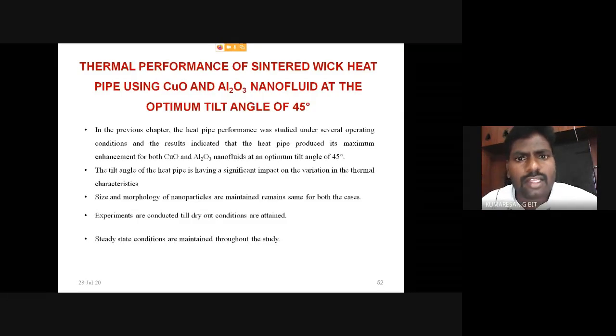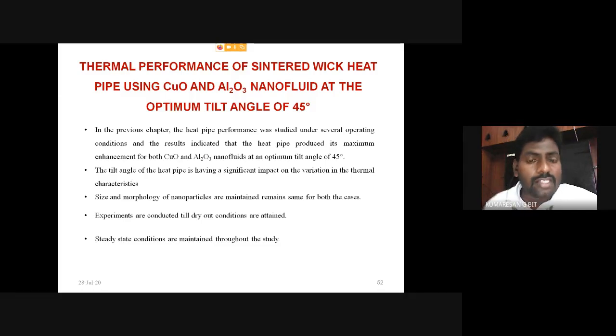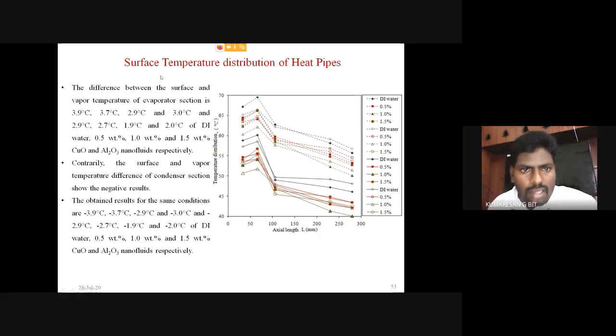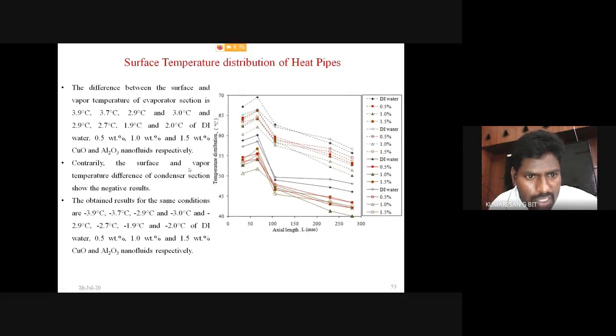Next, in another study, the thermal performance of the sintered wick heat pipe is compared using the copper oxide and aluminum oxide nanofluid at an optimum orientation of 45 degree. You see here the surface temperature distribution of both copper oxide and aluminum oxide heat pipes are compared, and the difference between the surface and vapor temperature of the evaporative section is 3.9, 3.7, 2.9 and 3 degrees Celsius. And for the aluminum oxide nanofluid, 2.9 degrees Celsius, 2.7, 1.9 and 2 degrees Celsius. Contrarily, the surface and vapor temperature difference of the condenser section shows the negative result.